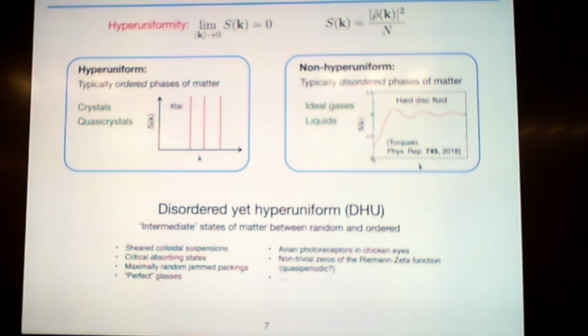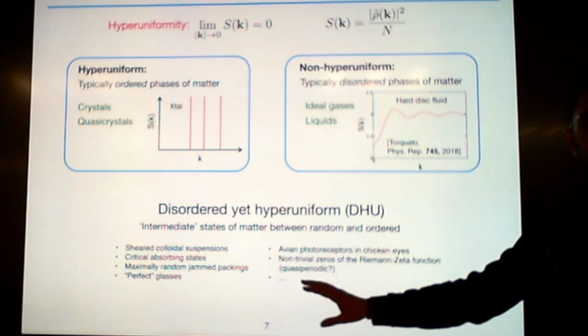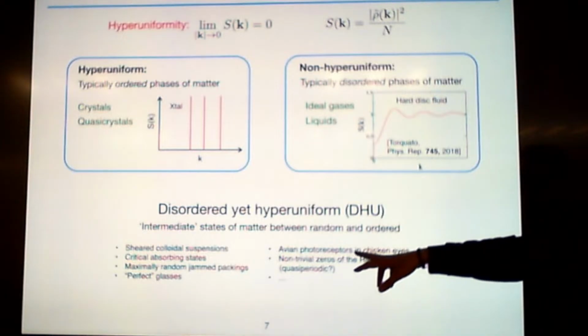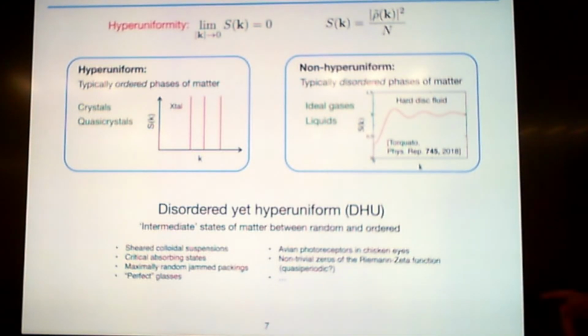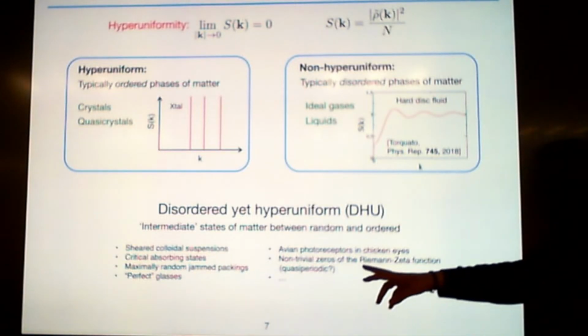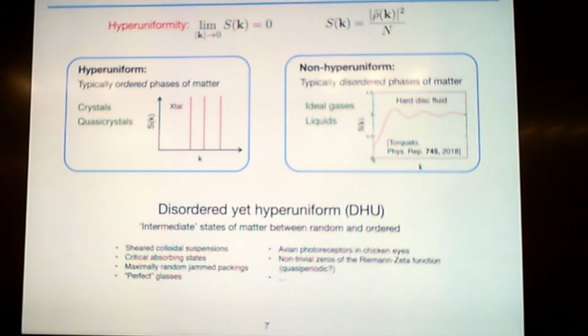So, obviously there are a lot of systems that are disordered and hyperuniform. We are not the first one. There's at least 10, 15 years of research on colloidal suspensions, random jammed packings, even biological photoreceptors in chicken's eye, more mathematical systems, for instance, the non-trivial zeros of the Riemann zeta function, etc. So these systems are kind of intermediate in that sense, that they look like liquids or disordered systems. There is no long-range positional correlation, yet they suppress density fluctuations just like crystals and quasicrystals do. And that's the interesting part of the story.